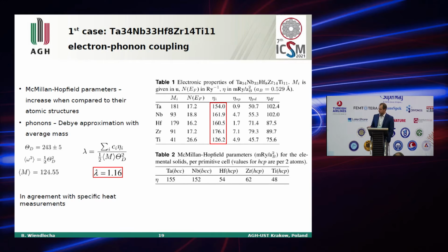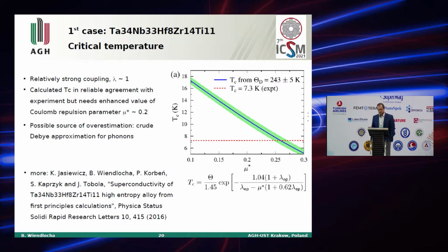And electron-phonon coupling: here are the McMillan-Hopfield parameters computed for this alloy. What we observed is that each atomic value is larger than the corresponding atomic value in its native structure. And using this simplification for the phonon spectrum, using the Debye temperature, we arrived at a coupling parameter of 1, which is in the strongly coupling regime. And this value relatively well explains the critical temperature. We have to use a slightly enhanced value of the so-called Coulomb pseudopotential, but this is probably related to the crude approximation for phonons.